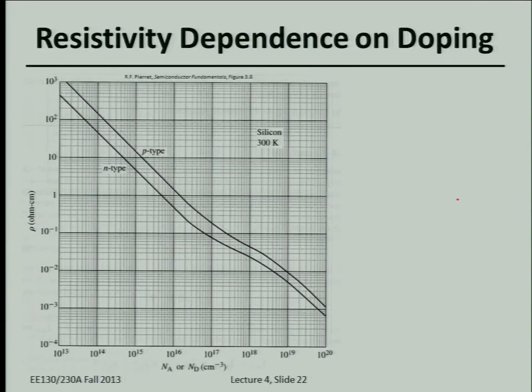So how does resistivity depend on doping? This is a plot from a textbook showing resistivity, rho, in ohm-centimeters, as a function of doping. This is on a log scale, because typically we can control the dopant concentration over many orders of magnitude, and we can control the resistivity over orders of magnitude. Remember I said it was from 10 to the 4 to 10 to the minus 4? So you can have like 8 orders of magnitude change in doping, and roughly 7 orders of magnitude change in resistivity.